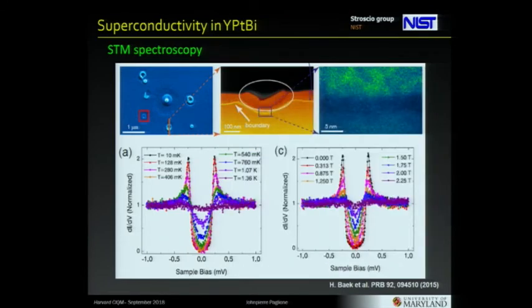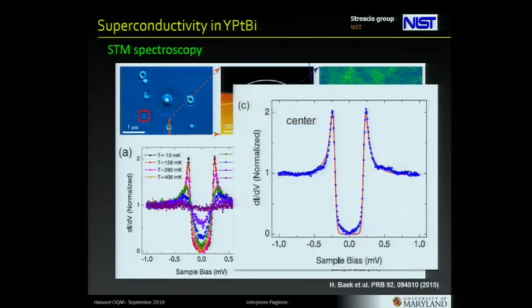Now there's a complication here. Joe did this millikelvin STM on surfaces, but the only cleave he could get was this cleave where there was some amorphous layer, which is probably some grain boundary. And he could anneal that with the tip and actually get some islands. What they show is that they're superconducting by proximity effect from underneath. So he would current anneal this part, and this would become a superconducting nano island, and do spectroscopy and all that on that. It kind of looks unconventional, but this is the proximity-induced state, so it's not clear what to say about that. But the vortices, oh shoot, I didn't show them.